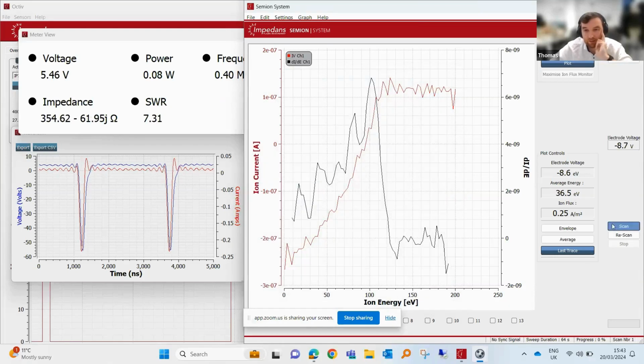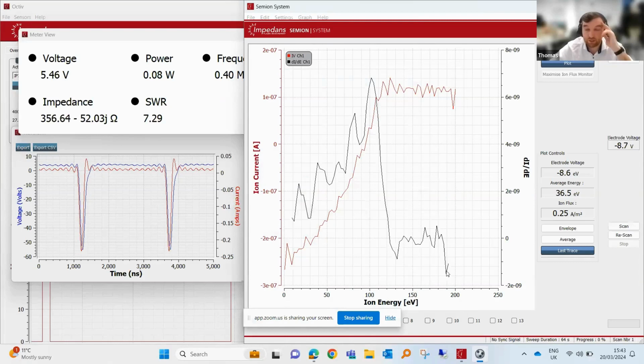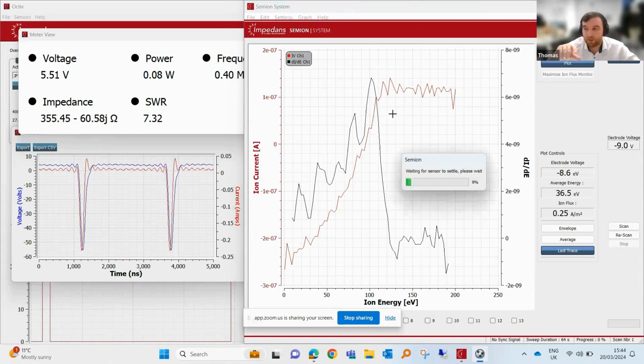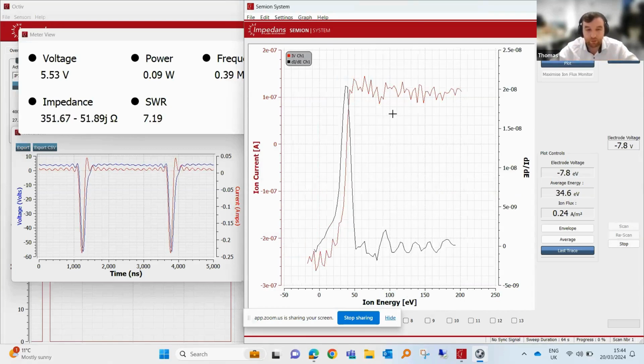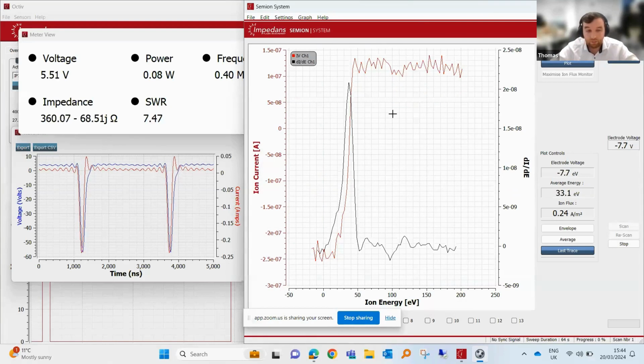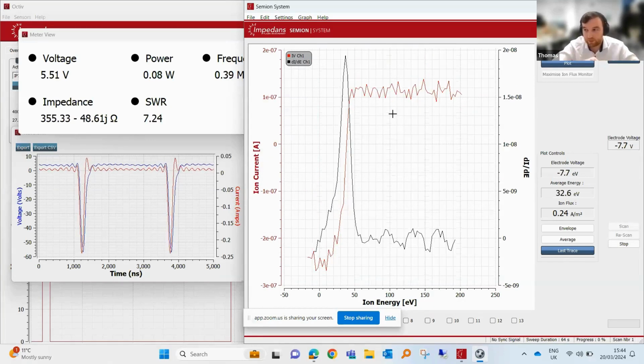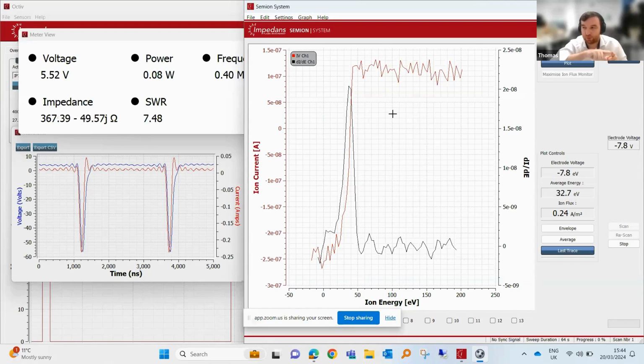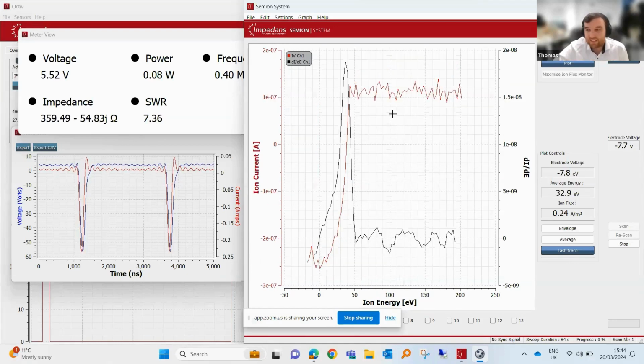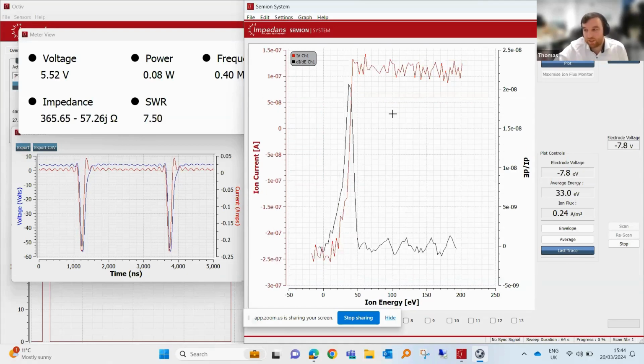Yeah, so you can do 0.1 eV, David, with the Semion. Yeah, we have clients who use these for low energy measurements. I can send you some papers. Send me an email and I can send you some nice papers where they've done precise low ion energy measurements. The only thing you have to worry about with the Semion with low ion energy measurements, if you have really high ion flux, there may be a voltage drop across those 200 kilo ohm resistors, which will change the data by up to 1 eV. We can help correct that, or our quantum system can actually measure before the resistors. You get more precise at lower energies there.